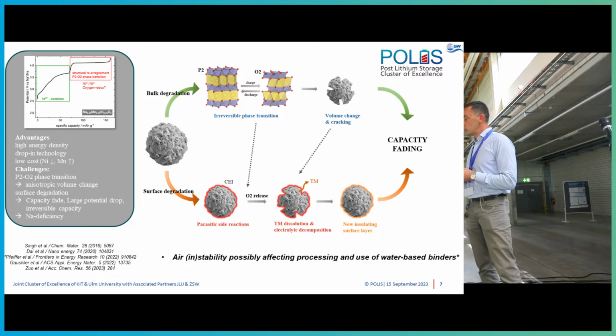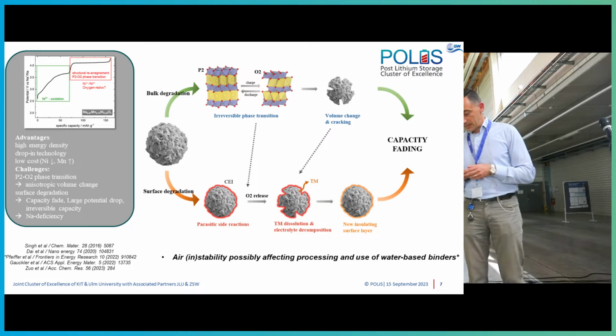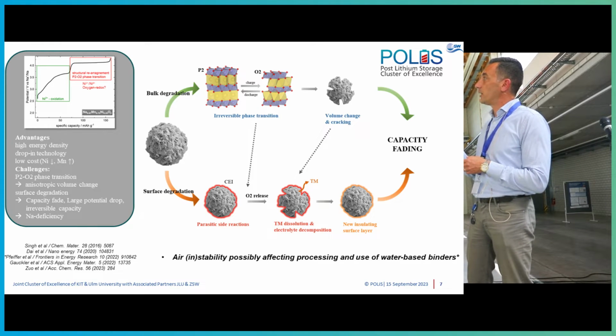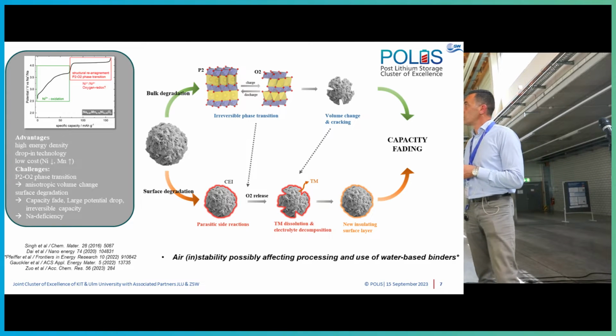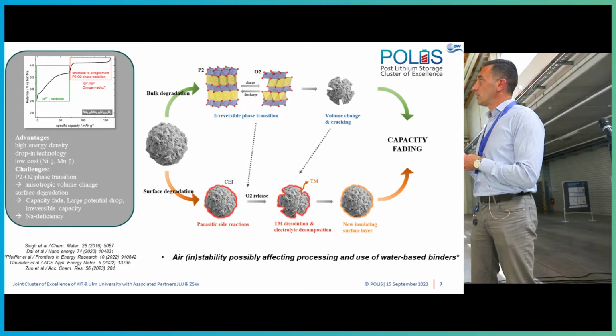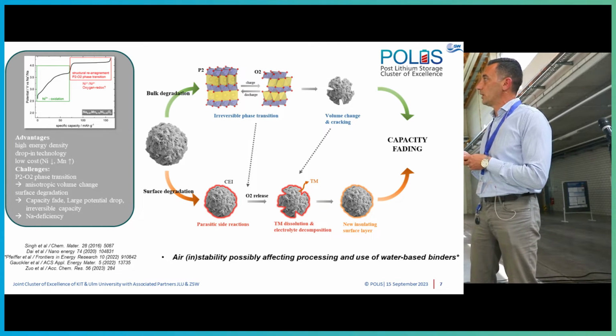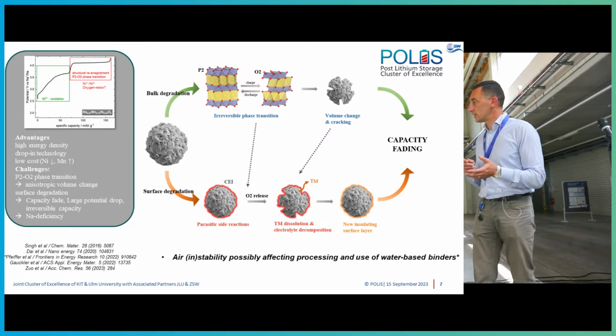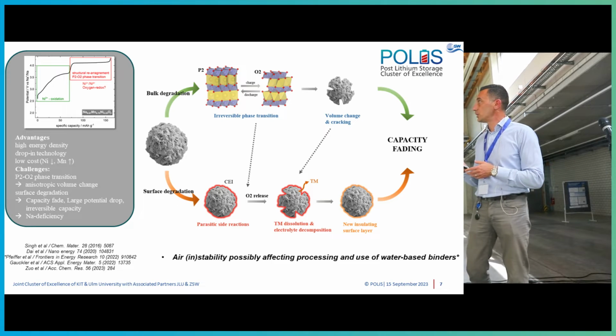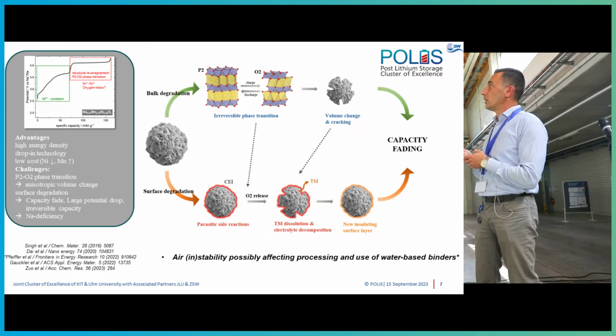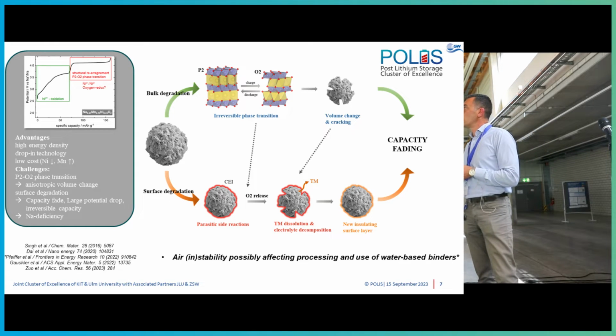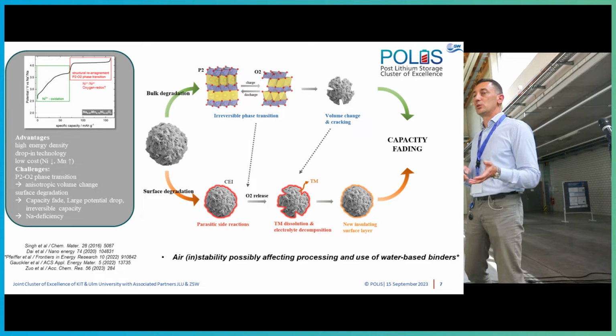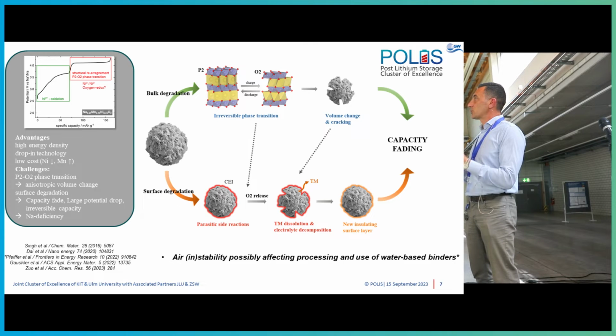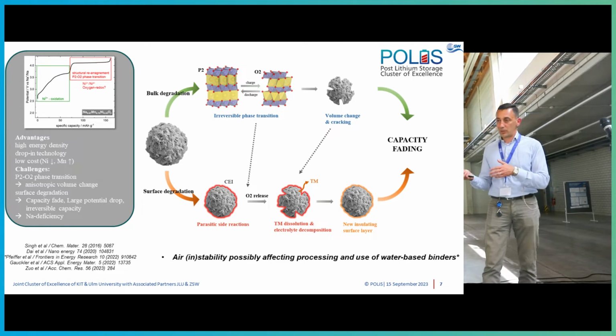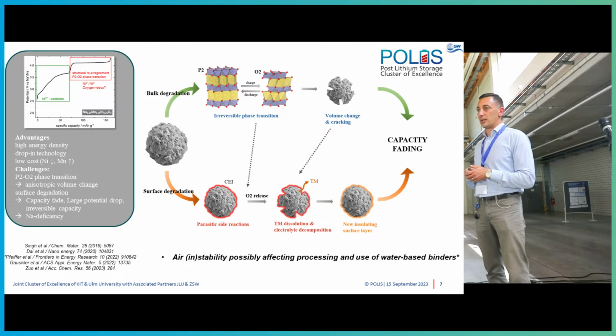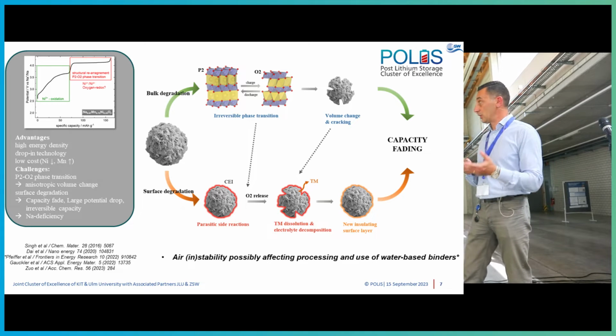For the P2 kind of material that we have, if we look at the upper left graph, this is a galvanostatic profile. When you start your oxidation, you have a sloping profile, and this is the nickel 2 plus oxidation. Then at one point you get into a plateau at about 4.2 volt, and this is where you have a phase transition from P2 to O2. It's expected that there you have nickel 3 to nickel 4 plus oxidation. You might have some oxygen redox reaction, eventually some oxygen evolution.